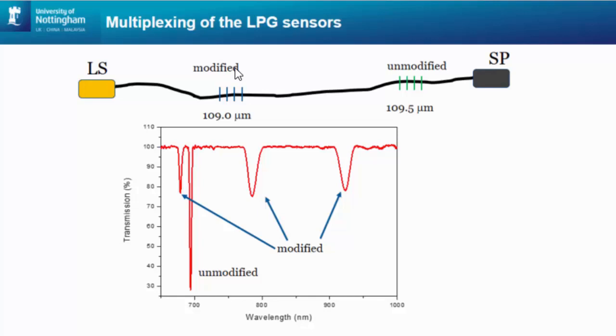In order to overcome this problem, what we can do is multiplex this optical fiber, so we can have two sensors with slightly different grating periods, which lead to different attenuation bands present in the transmission spectrum. And we can modify one grating with our sensitive layer and leave the other grating unmodified, which will be sensitive only to temperature. There's no absorption site there, so no gas will influence the position of this peak here, but it is temperature sensitive, so we can measure temperature. So we have a response to ethanol, and we can measure temperature.